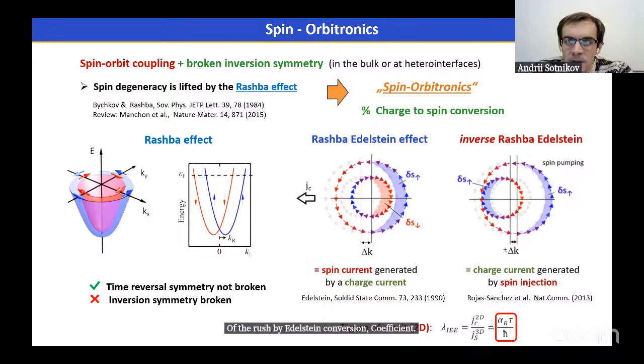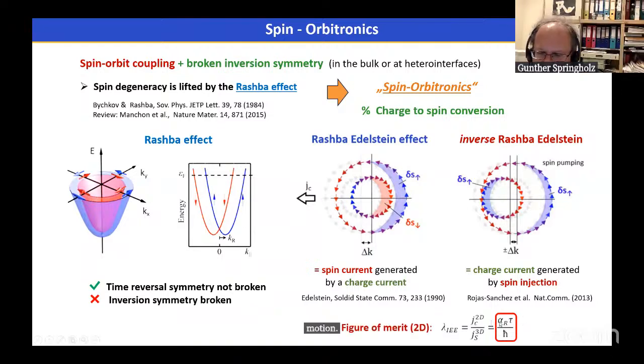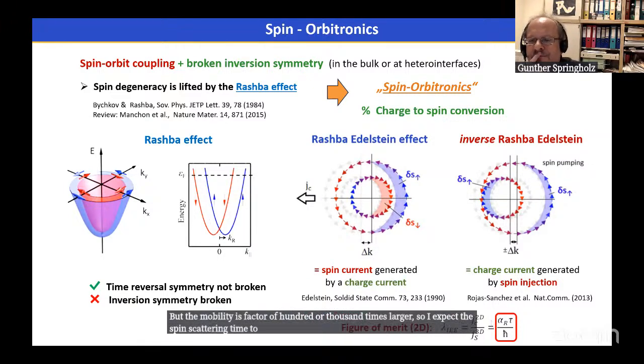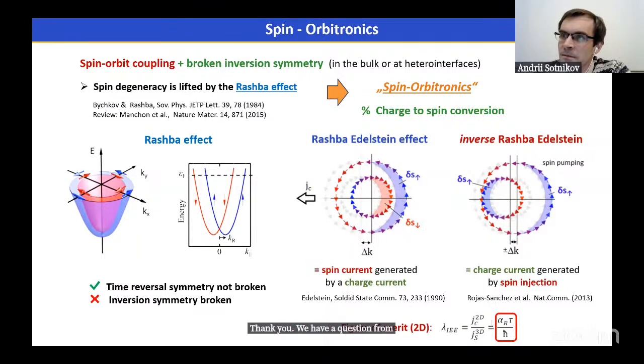Okay, but you expect that it should be larger for your system than this conversion? As I said, the Rashba constant of lead germanium telluride is only half of that of germanium telluride, but the mobility is a factor of 100 or 1,000 times larger. So I expect the spin scattering time to be longer, and therefore get a higher figure of merit of the system. Thank you. We have a question from Sergei Shevchenko.